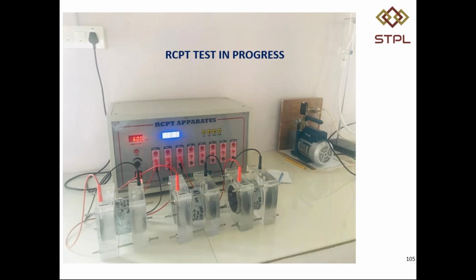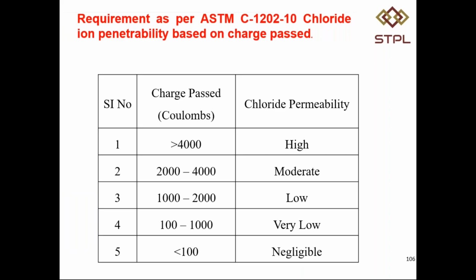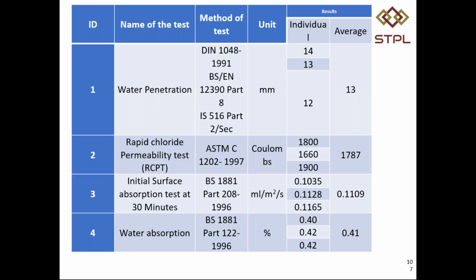Another important test we conduct, especially for concrete made in coastal areas, is the rapid chloride penetration test, the RCPT. The RCPT is done to check the permeation of chloride ions into a concrete. It takes about 6 hours, a simple test, and we need to have this equipment to carry out this test. And this table given in ASTM C1202 gives the requirements. If you have made a good concrete by good gradation of aggregates, good quality of aggregates, the permeability values can be as low as 1,000 to 2,000, or maybe less than 1,000 coulombs also. So this is a low permeability.